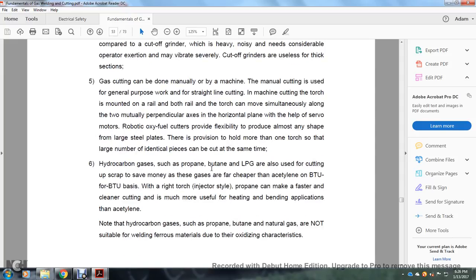Hydrocarbon gases such as propane, butane, and liquid petroleum gases are used for cutting up scrap to save money. These gases are far cheaper than acetylene per BTU. With the right torch injector style, propane can make faster and cleaner cuts and is much more useful for heating and bending applications than acetylene. Note that hydrocarbon gases such as propane, butane, and natural gas are not suitable for welding ferrous metals due to